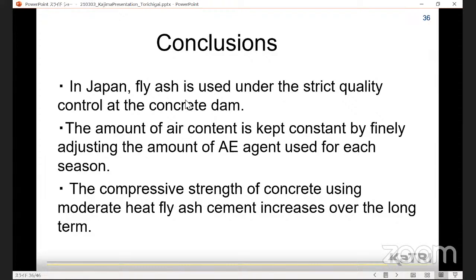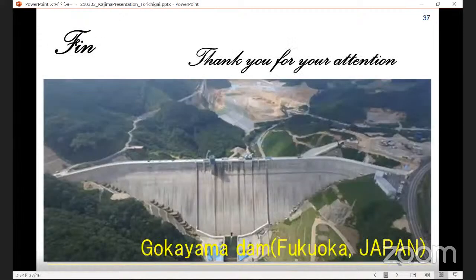In Japan, fly ash is used under strict control at concrete dams. The air content is kept constant by adjusting the amount of air-entraining agent for each season and each day. The compressive strength of concrete using moderate heat fly ash cement increases over the long term. That's the end of my presentation.